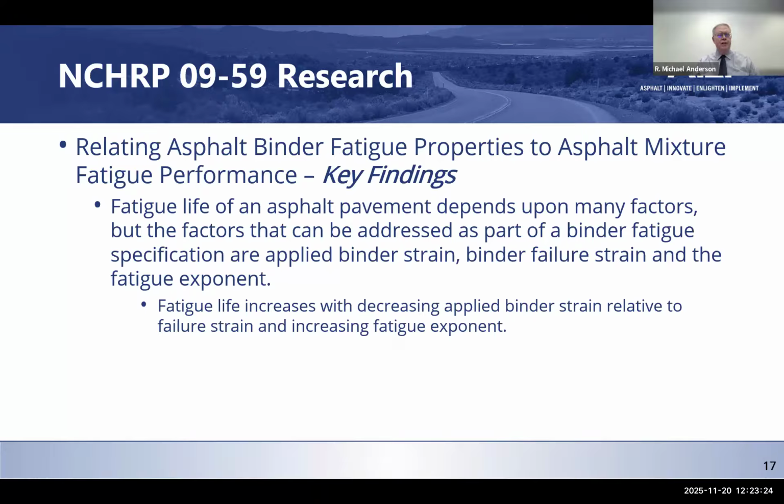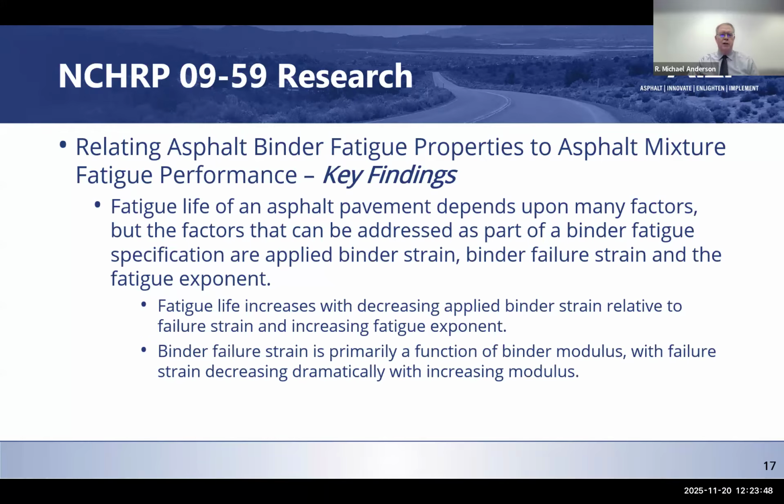So fatigue life increases with decreasing applied binder strain, which is not unlike what we talked about in pavement structure. If you make the strain less, it's going to increase the fatigue life and the cracking resistance. So decreasing applied binder strain relative to failure strain, but also increasing the fatigue exponent.